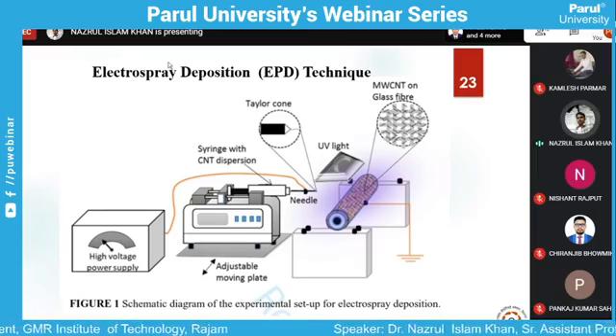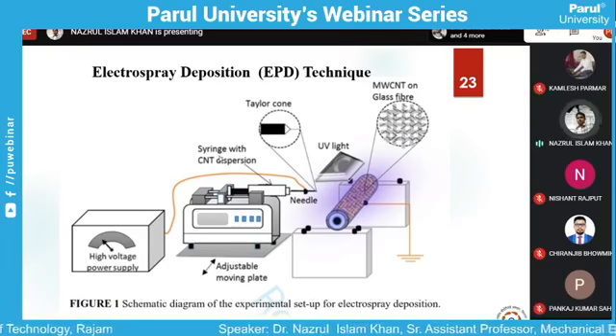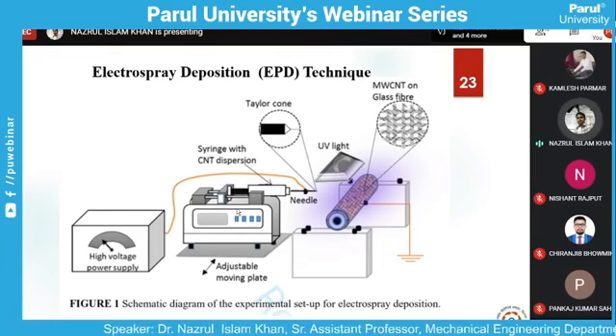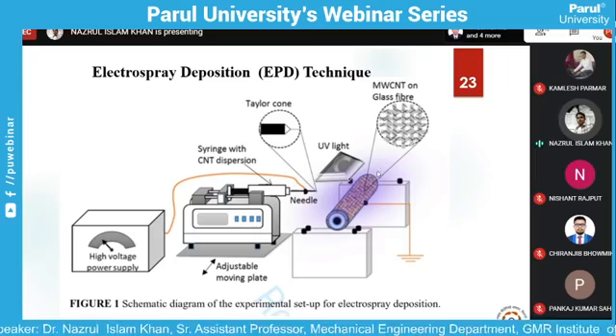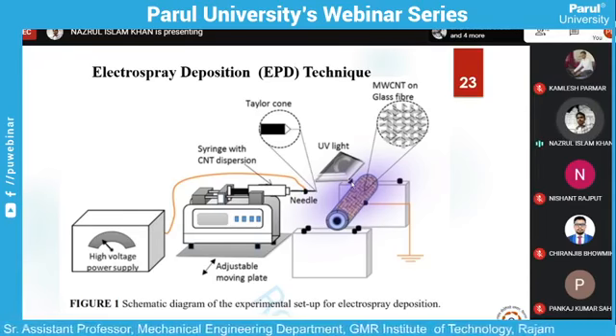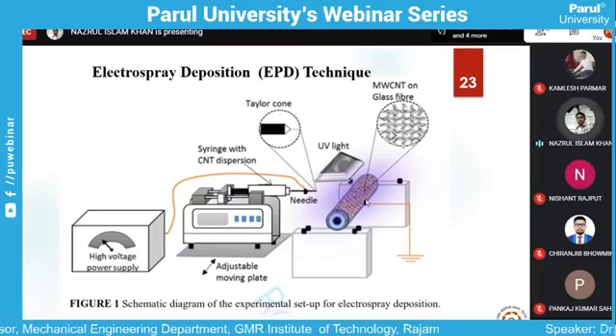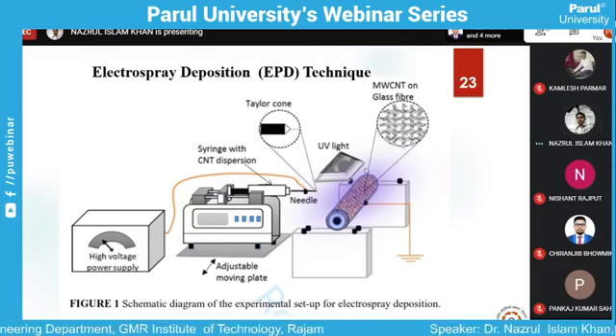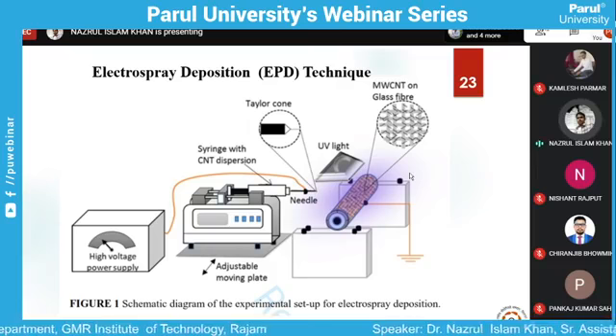So for that, electrospray deposition technique is one technique where you have a needle, like a syringe, containing the resin with CNT dispersed in it. Using an adjustable or movable plate and applying pressure, this resin comes outside onto a roving of glass fiber. Between this needle and the glass fiber, there is a very high voltage applied. If you apply high voltage, the spray of resin becomes umbrella shaped, or a very fine micro spray of resin forms, which gets easily deposited on the glass fiber.